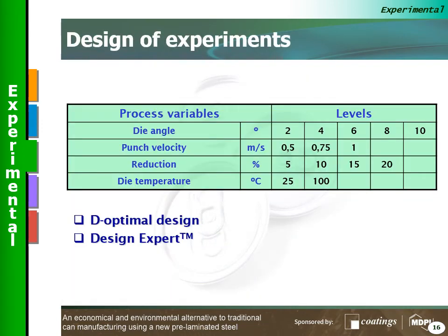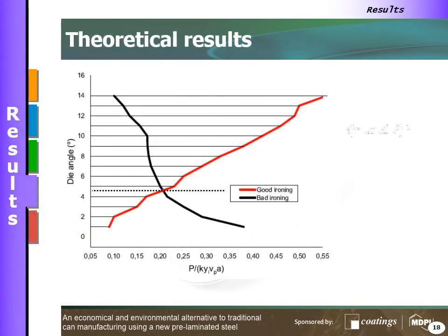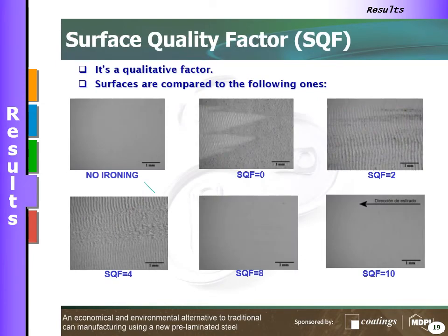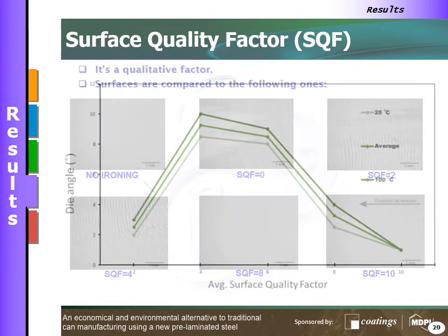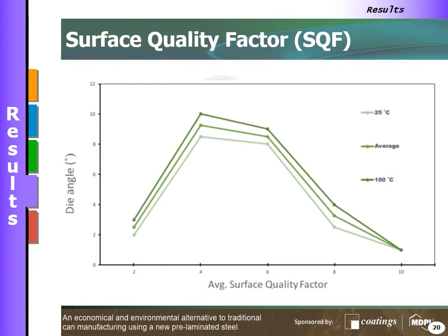These are the process variables we use for the design of experiments. The results of the upper bound model show that we have an optimal angle of 4.8 degrees. The surface quality factor is a qualitative factor in which the surfaces are compared to the following ones. And in this graph, it's possible to see the die angle versus the average surface quality factor, and it's possible to see that with angles of 4 and 6 degrees, we get good ironings.